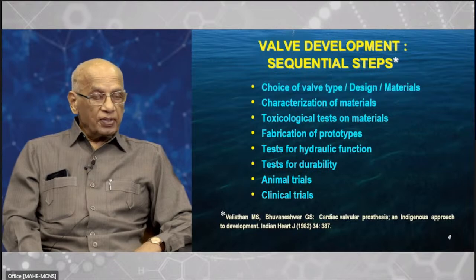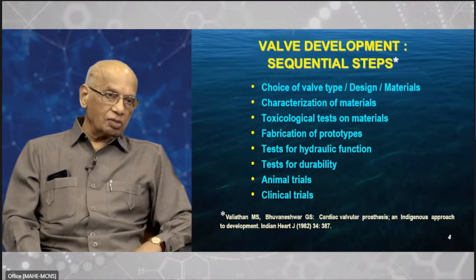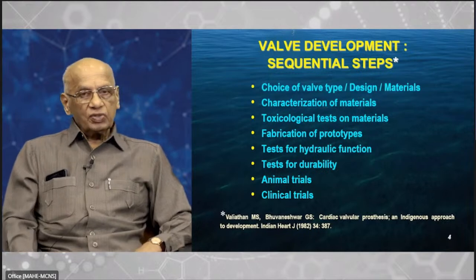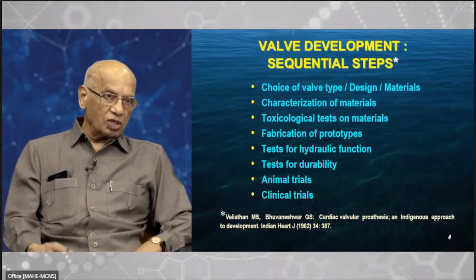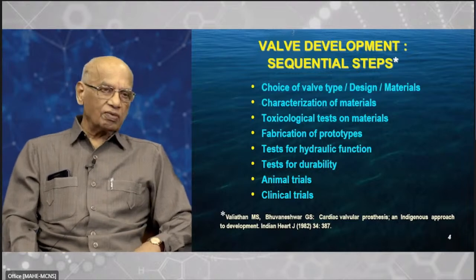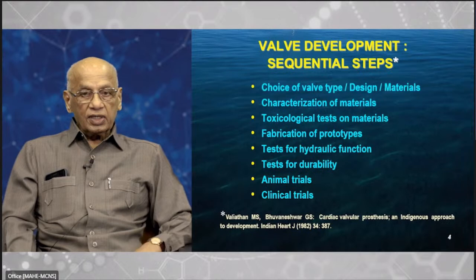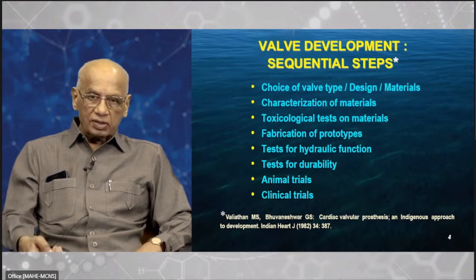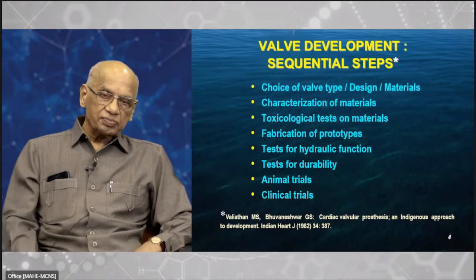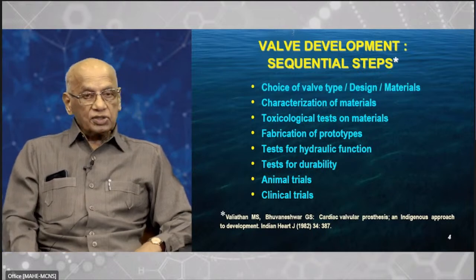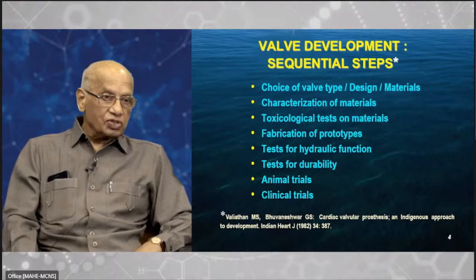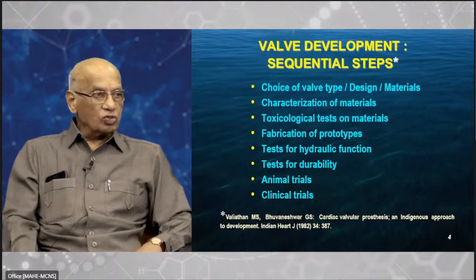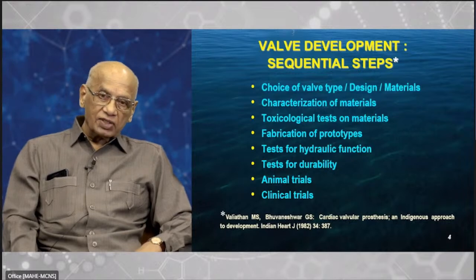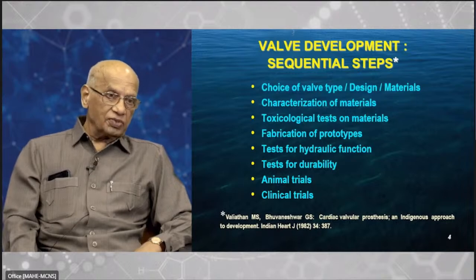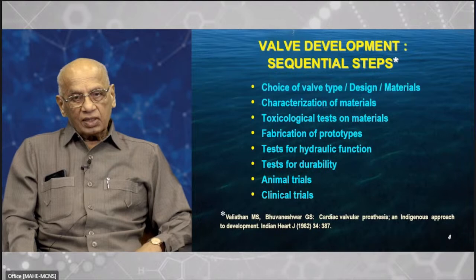That's also not easy. The animal has to be sufficiently large, about comparable to the human heart, and we chose sheep for that. From Tamil Nadu, we could get sheep weighing around 45 kilograms. And their heart size will give a good fit for this valve, our size. Now those animals have to be anesthetized. The operation requires the same skill, the same care as you do for humans. And they have to survive 3 months in good condition. Then electively, not because they are sick, this is required, it's a kind of painful thing to do.